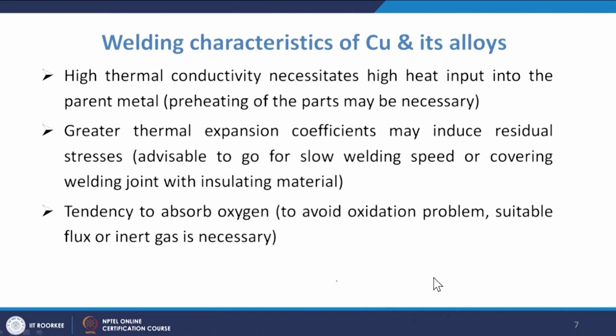High thermal conductivity necessitates high heat input into the parent material. Preheating of the parts may be necessary. The greater thermal expansion coefficient may induce residual stresses, so it is advisable to go for a slow welding speed and cover the weld joint with insulating material. Tendency to absorb oxygen: to avoid the oxidation problem, suitable flux or inert gas is necessary.